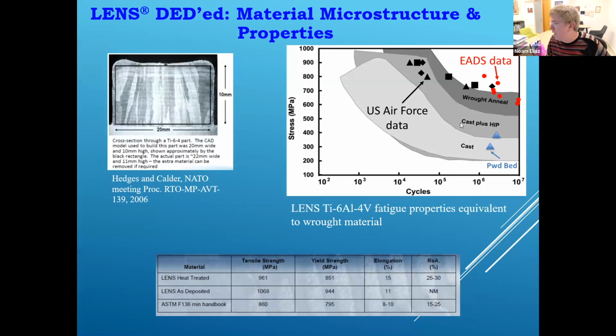On the right-hand side, you can see US Air Force data. This is for titanium 6-4. You can see the difference in the S-N curves, or the dynamic mechanical properties, between the cast material, the cast with hot isostatic pressing treatment, the wrought annealed, and then you can see the data for the DED. So you can see that in this case, the dynamic properties that you get with the DED are better than the powder bed, the blue triangles that you see at the bottom, but also compared to the traditional wrought or cast alloys.